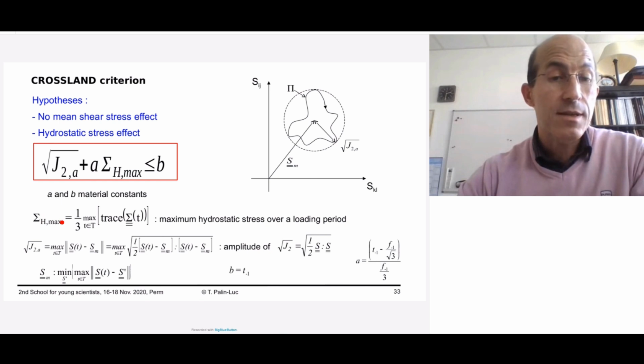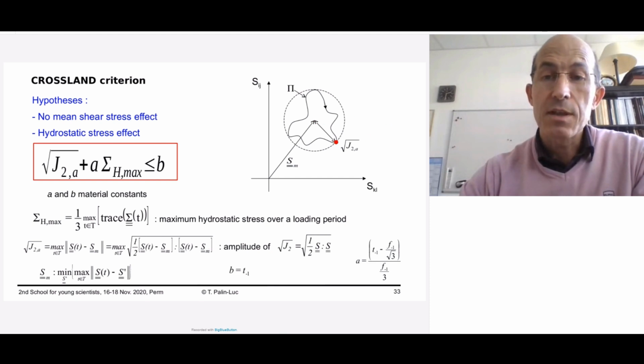So the maximum hydrostatic stress is easy to compute. This is the maximum value of the trace of the stress tensor in each point. And the amplitude of the deviatoric shear stress is defined by this equation, which is nothing else than the radius of the sphere in the deviatoric space. So this is the radius of the hypersphere surrounding the load path in the deviatoric domain or space. And the two parameters A and B representing the material properties are identified from two fatigue resistances in high cycle regime, typically at 10 to the 7th cycle. The fatigue resistance in reverse tension gives B, and the slope A is given by a combination of the fatigue resistance in torsion under fully reversed loading and under bending under fully reversed loading.